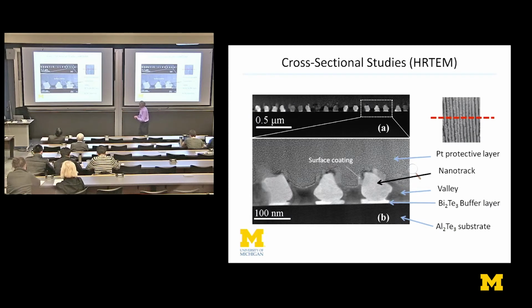And I want to point out here, and this is like what you might call a smoking gun, and that is the shape of these structures. Remember, this started as a thin film here, a nice, smooth epitaxial film before we hit it with the laser. And now you see it's producing these very interesting shapes between what we're calling the wires here. In these valleys, they have very interesting shapes. And that is going to tell us, as I'll point out in a moment, what is the basic mechanism that produces these kind of nanostructures.